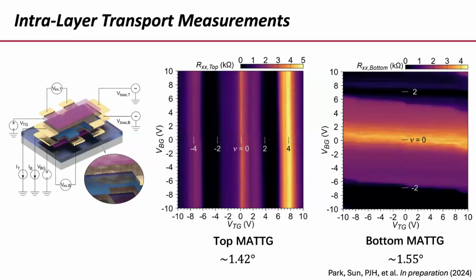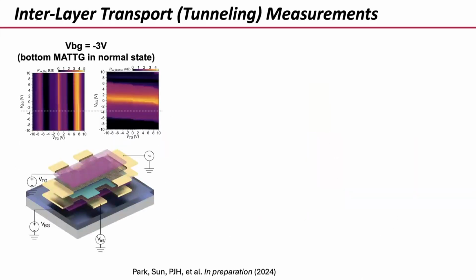But for the rest of the talk, I'm going to use the bottom magic angle trilayer as a tunneling electrode in the normal state. So I'm going to choose my back gate voltage here so that the bottom magic angle trilayer is in a relatively featureless normal metallic state, no superconductivity, no insulating. And with this bottom magic angle trilayer graphene, I'm going to explore the top magic angle trilayer graphene, superconductivity, etc. So let's choose this gate voltage on the bottom gate. This is a normal electrode now, and then I'm going to sweep the top gate.